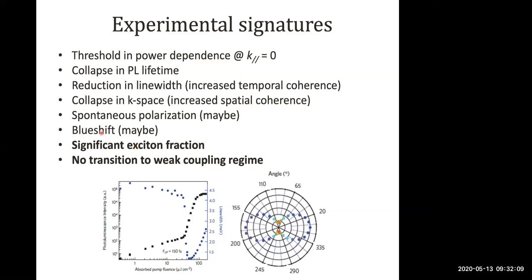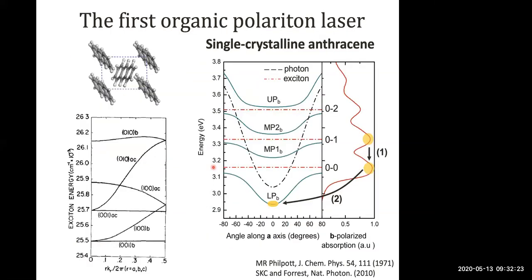And of course, polariton lasing itself implies that you must have some significant exciton fraction in the mode, and that you pump at a density such that you do not have a transition to the weak coupling regime. Okay. So the first material used for polariton lasing was single crystalline anthracene. Here on the left, we have the crystal structure of anthracene. So in a single unit cell, we have two inequivalent molecules.